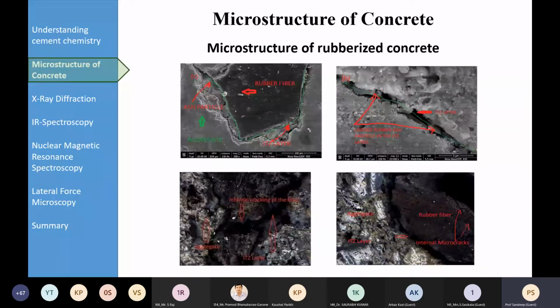Again, from another angle, if you see, this is the rubber fiber, and you can see this interfacial transition zone. This is the interfacial transition zone, and within this interfacial transition zone, the rubber ash particles are lost. So that's an interesting thing. There's a rubber fiber, there's a hydrated cement paste, a CSH gel, and between them there's the interfacial transition zone.